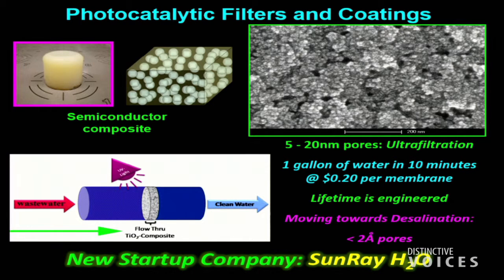So we're taking these materials that have your tater tot, we slice them up into thin little discs, which I'm passing around now. We heat it up, and when we do this, we burn out the polymer. Those little particles of this catalyst fuse together, but when they do, they leave behind pores, holes. So now what we're doing is taking these membranes and putting it into a one-step process where you can flow wastewater through, shine light on it, and hopefully out comes clean water. So that's what we're moving towards.